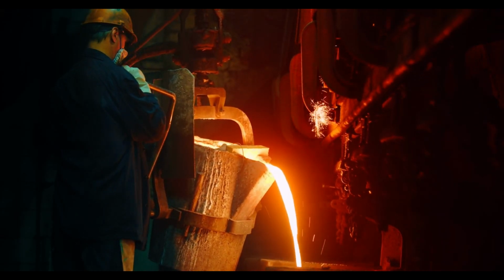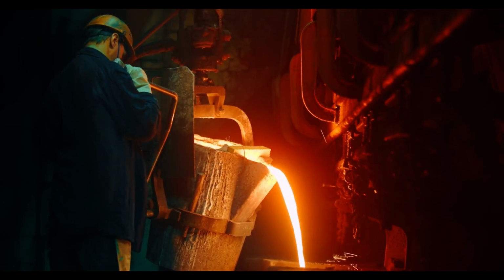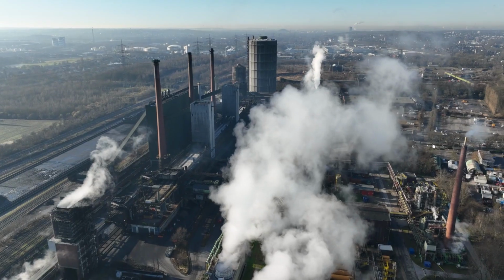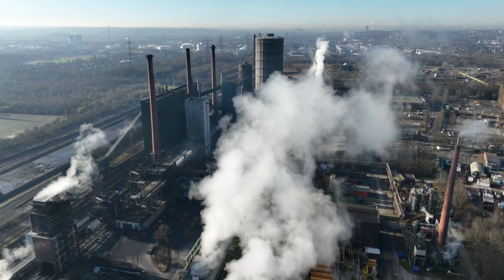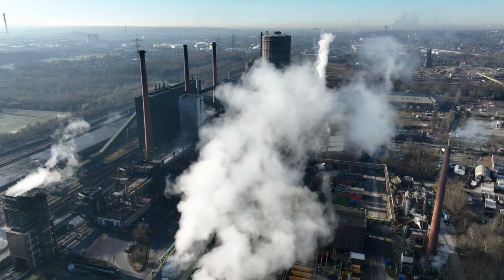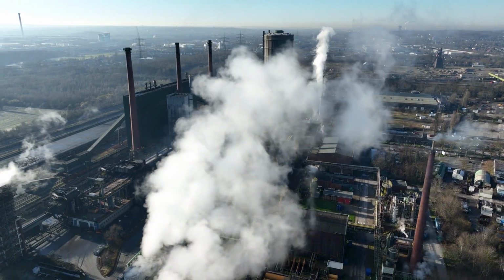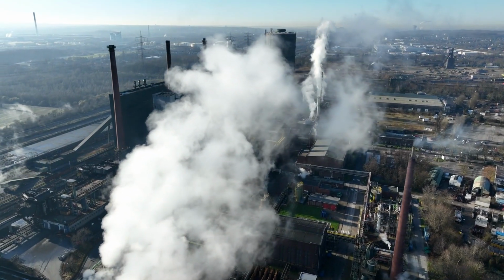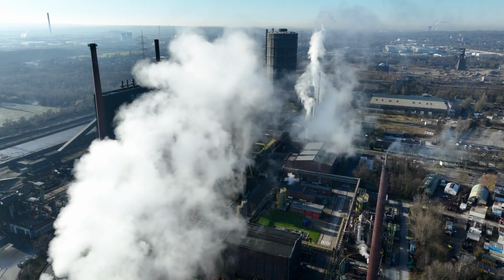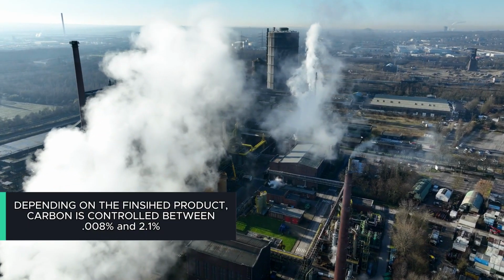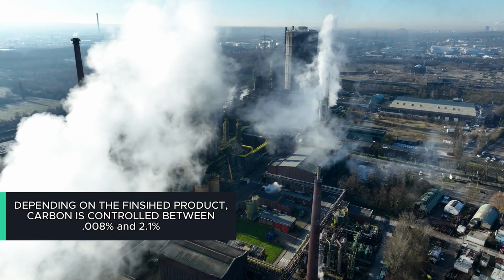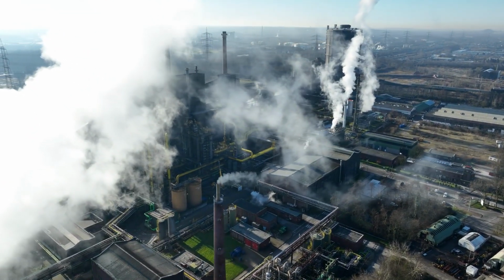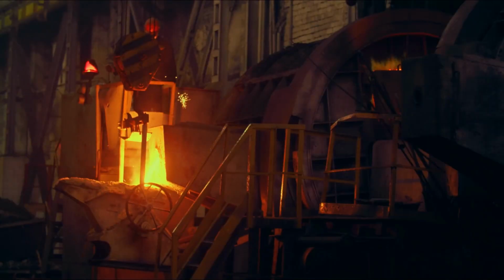So the pig iron travels while still molten to a basic oxygen furnace, where a supersonic lance blasts pure oxygen into the liquid metal. The oxygen burns off the excess carbon. For structural steel, it drops below 0.3%. For different grades, carbon is precisely controlled between 0.008 and 2.1%. That number, the carbon percentage, is what determines whether you are making a bridge beam, a surgical instrument, or a coiled spring.